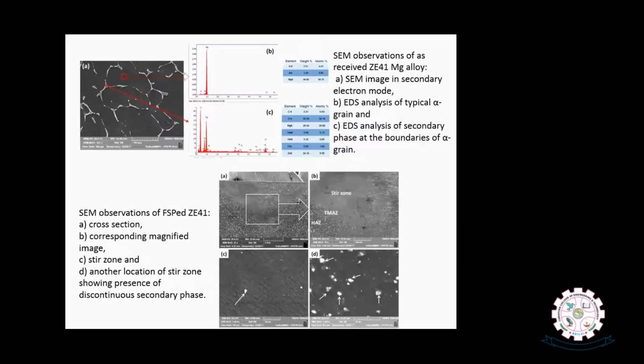And interestingly, after processing, you can see here in these scanning electron microscope images that in the stir zone the intermetallic phase has totally disappeared, and in some regions, as shown in the bottom image, the network-like structure as observed in the base material, the top ZE41 SEM image, the network-like structure of the magnesium zinc intermetallic phase was totally disturbed, and discontinuous small particles distributed in the matrix can be seen in the bottom FSP region. So that indicates that an excess amount of zinc has been introduced into the magnesium lattice, and supersaturated magnesium zinc grains were developed, and the intermetallic percentage was decreased.